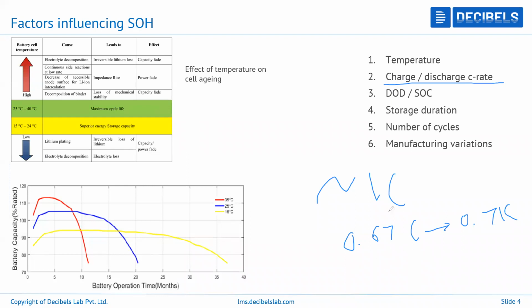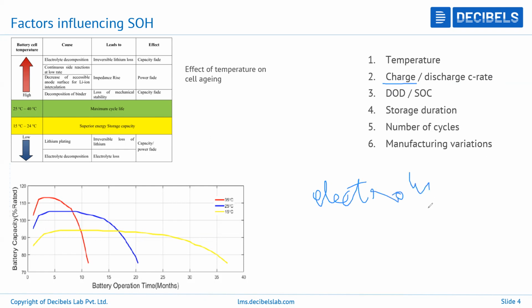But if you continuously charge at 1C or higher than 1C, then it will once again tear away at the internal components. Most notably, the one that will start to decompose first is the electrolyte. Once you continuously supply very high charge currents, your electrolyte will start to degrade, or basically you can say it starts to form unwanted compounds. You can call these passive compounds. They don't participate in any reaction, and usually they act as a chemical barrier, right? So this is the effect of having very high charge rates.